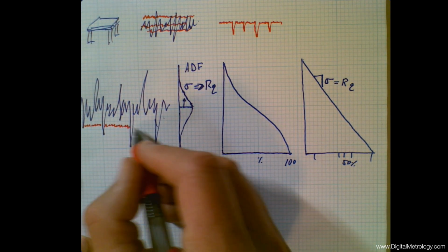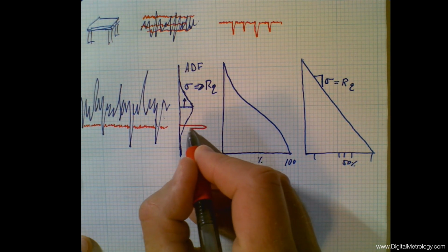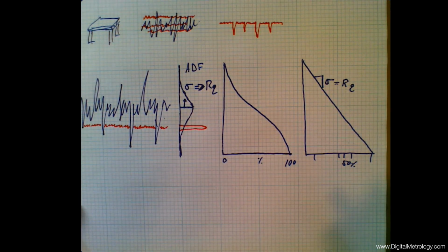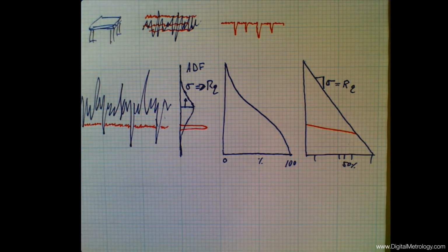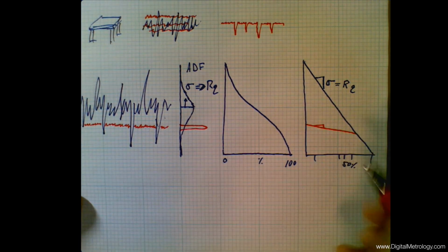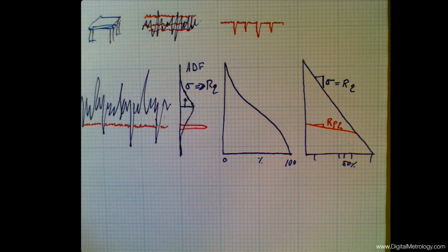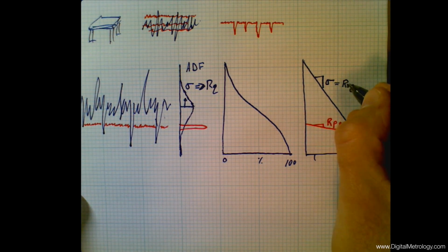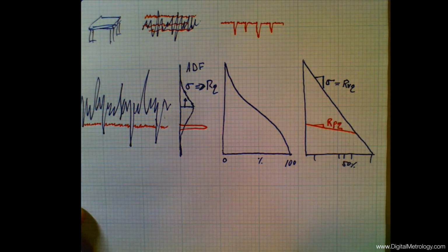Let's add another random surface. We're going to plateau or wear our way into the surface. And this is a concept put forth by Williamson, the famous tribologist in the 1960s. And he showed that another surface moving through the original base surface is also random, and it would also have a straight line in this world. Now, we can look at this straight line also as an Rq. Let's call this the roughness of the peaks in the Q parameter family. And let's insert a V here, and we have the roughness of the valleys in this new Q parameter family.